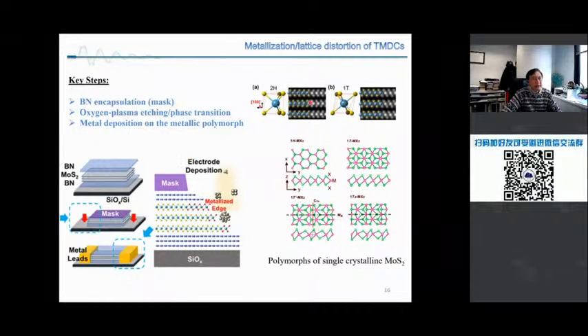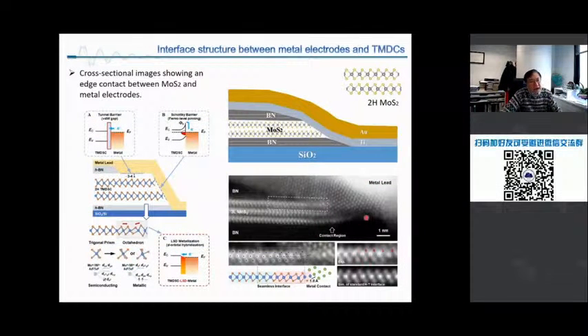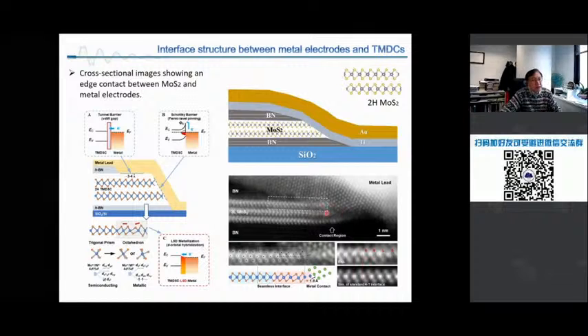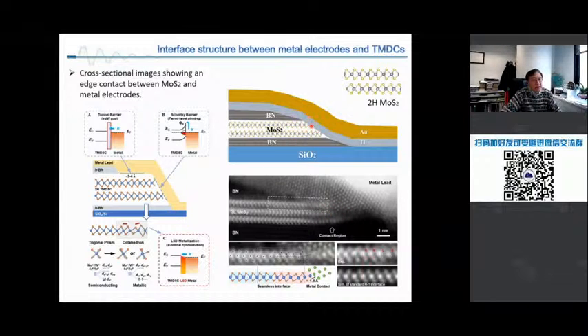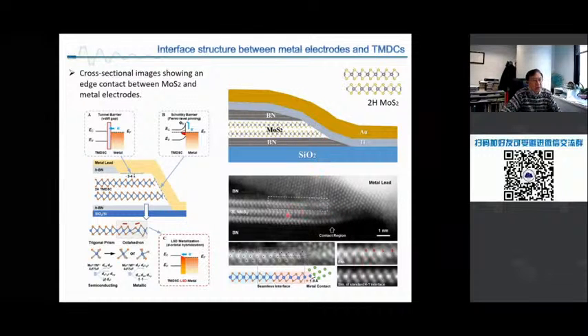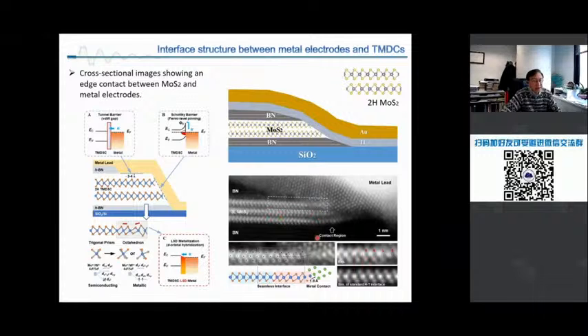So once again, I showed the simulation image of the so-called 2H to 1T phase. The principle is that we make sandwich structures, and then in each area we make a window and make a phase change to metallize the channel materials. So I show you one of the atomic resolution images of this device and the interface between the 2H and the so-called 1T phase.